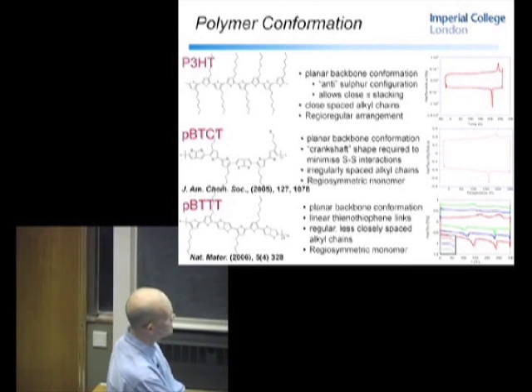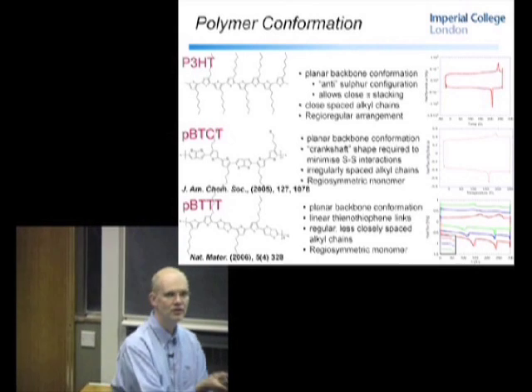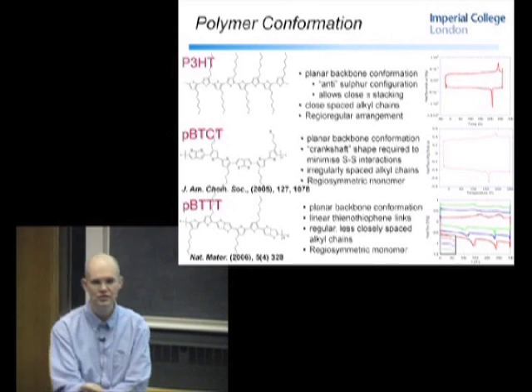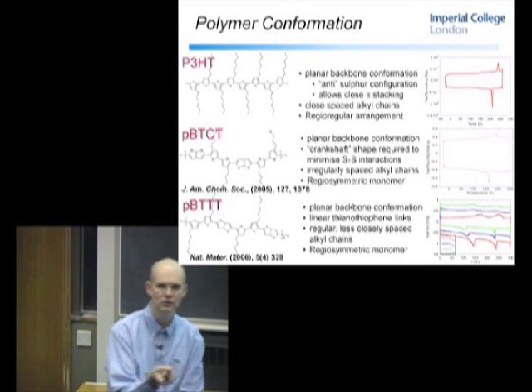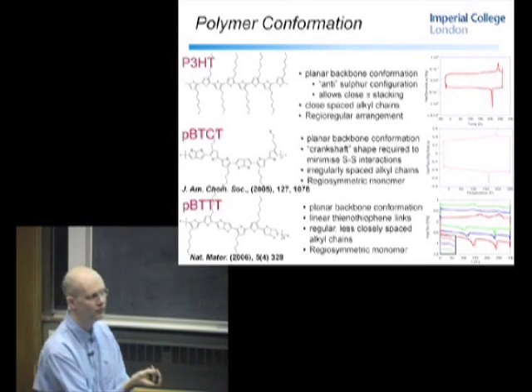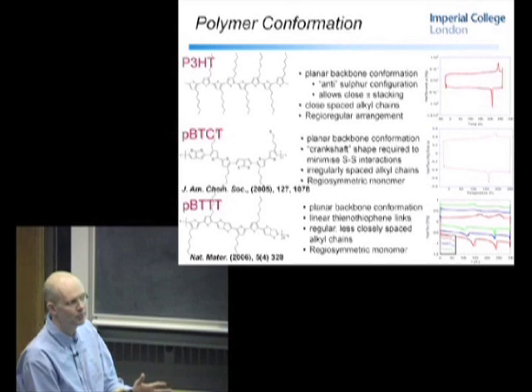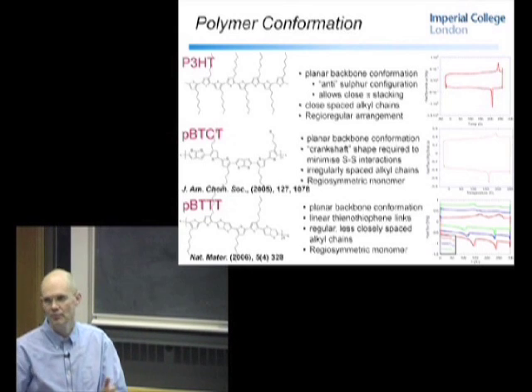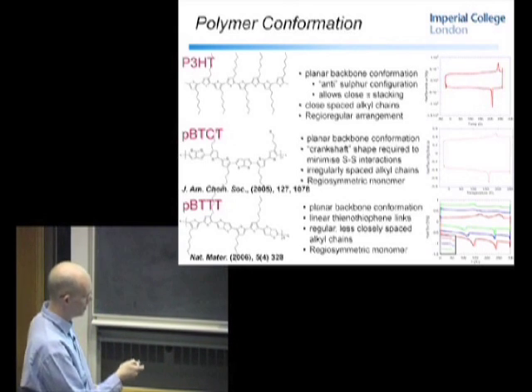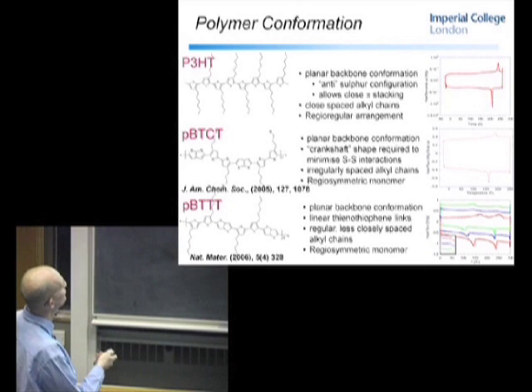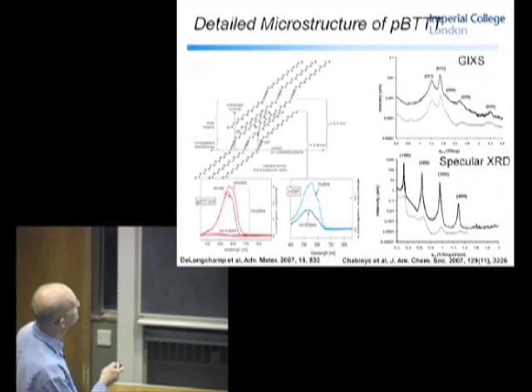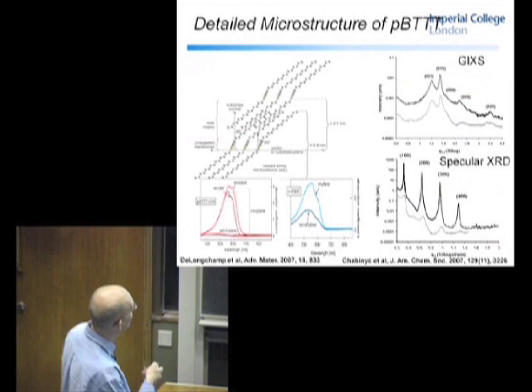And when you process in this liquid crystalline phase, you can take advantage of the lower viscosity of liquid crystalline polymer materials in the melt phase, and this allows this self-assembly to occur. So the annealing step is much more efficient, and so this gives rise to improved properties. This is PBTTT. If we look at the